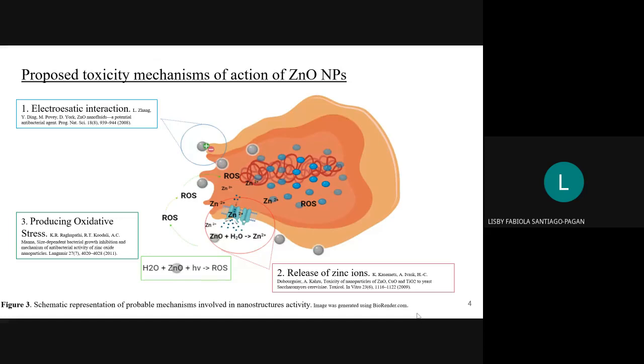Researchers believe that this mechanism was due to the semiconductor properties of the zinc oxide. For example, Raghupathi and co-workers showed that there was an increase in reactive oxygen species production from the nanoparticles when they were exposed to UV and visible light. It was believed that there was a correlation between the UV and visible energy absorption, photon reaction, and the release of reactive oxygen species.